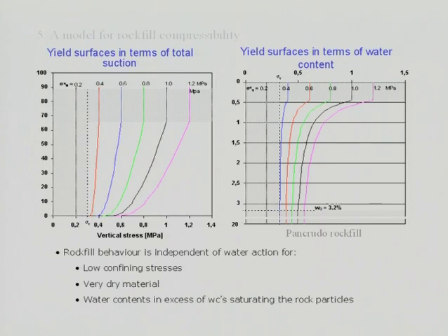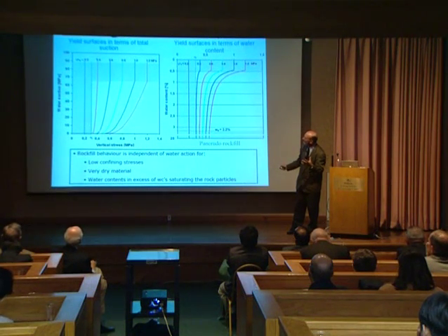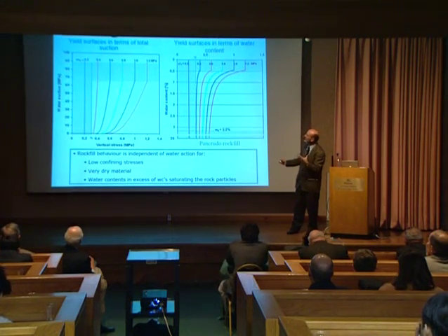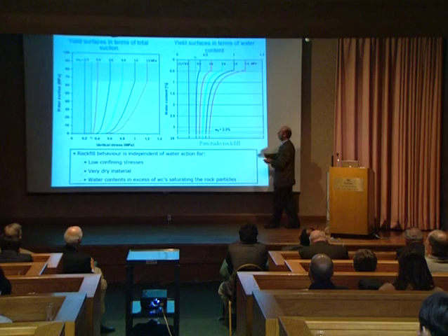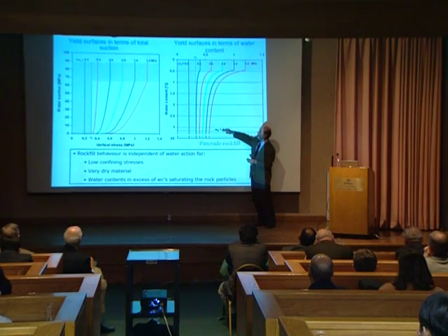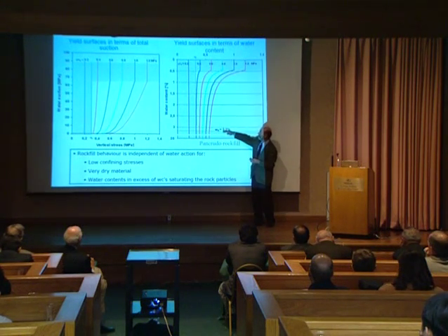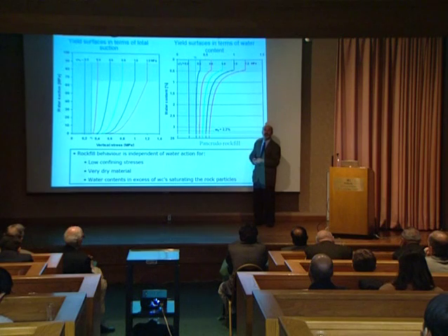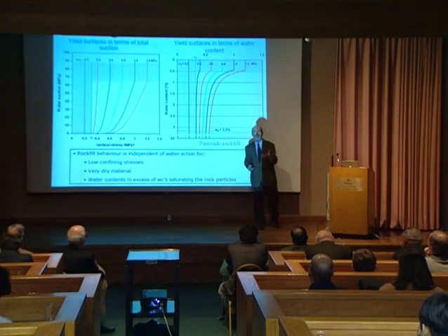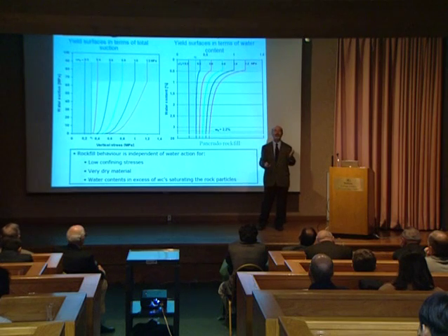If the stress applied is lower than the threshold stress, nothing should happen, no effect of water. So the effect of water can only be measured in the white area in both graphs. If you use water content, nothing will happen for water contents in excess of 3.2% for this particular rock, because beyond 3.2%, the relative humidity essentially is 100%. So it doesn't matter that you have 3 or 4 or 5 or 20% water content, nothing will happen.